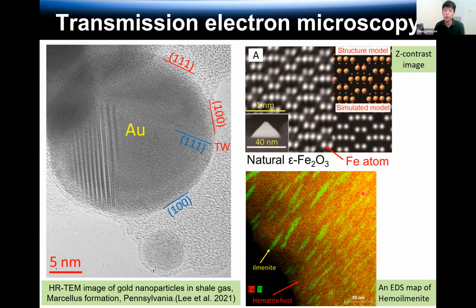Also, TEM can provide chemical information. This is the EDS mapping of a hemoilmenite sample. Look at the scale, this is 50 nanometers. This is exsolution lamella of ilmenite and host hematite minerals. This hemoilmenite has a strong, unusual remanent magnetic property, and this magnetic property is strongly related to these kinds of nanoscale exsolution lamella textures. So this is a good example: the nanostructure can explain the unusual strong magnetic property of the rock.